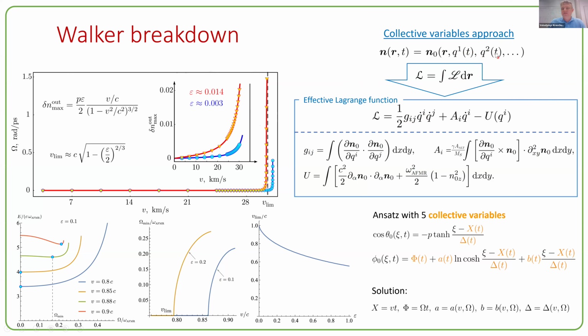Collective variables here, these are Q's. And here we see in this Lagrangian that we again obtain some additional term which is determined by our altermagnetism, and here it plays the role of some gauge field. And we consider this problem for 5 collective variables, which are domain wall position, domain wall width, domain wall phase. This term is actually also known for conventional domain walls in conventional antiferromagnets.